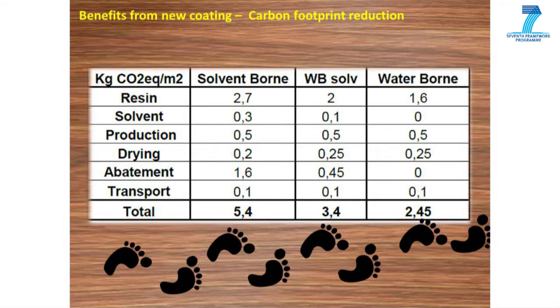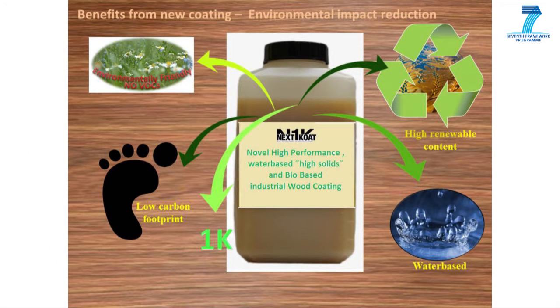We can see that the carbon footprint of solvent-borne coatings is 2 times higher than the carbon footprint of NextKoat technology, and the carbon footprint of waterborne solvent coatings is almost 1.5 times higher than NextKoat. The newly produced waterborne one-component coating in this project directly and indirectly influences the key environmental impacts. Compared to the other coatings, the new waterborne solution results in no emission to the atmosphere or solvent-containing waste streams. It is characterized by low VOCs, made of a highly renewable source with a low carbon footprint.